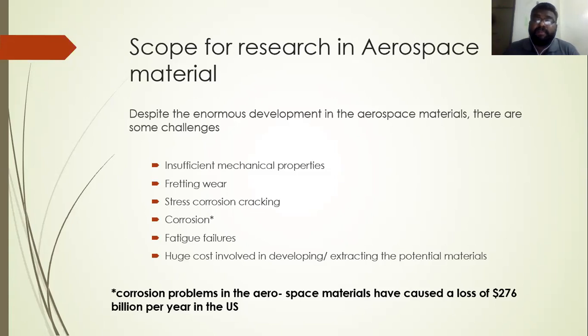And then second is fretting wear. That is the upcoming very important problem in the engine components. Fretting wear is where the relative motion doesn't exceed 100 microns, a very small vibration kind of relative motion between the components. That will create fretting debris, the wear resultant, and that debris will not even escape from that contact. So it will just remain in between this small relative motion, and that will create a crack, and that crack will lead to a fatigue failure also, which is called fretting fatigue. That is very insidious and very hazardous, and a lot of engines have failed during the flight itself due to this kind of problem. So that has to be addressed properly.